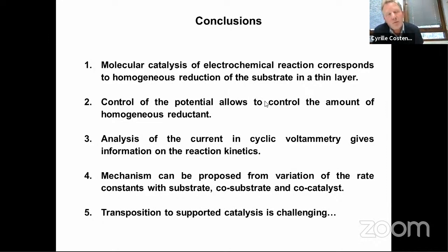Or if you have a substrate which is a very small molecule that diffuses very fast in the solution, you might be closer to the situation when there is no limitation by diffusion of the substrate, but you might have other limitations, for example the solubility, which is a problem if you try to reduce CO2 in water, because the solubility is small. So then you have to use tricks such as using a very thin layer or using a gas diffusion layer. And of course, there are limitations in that sense.